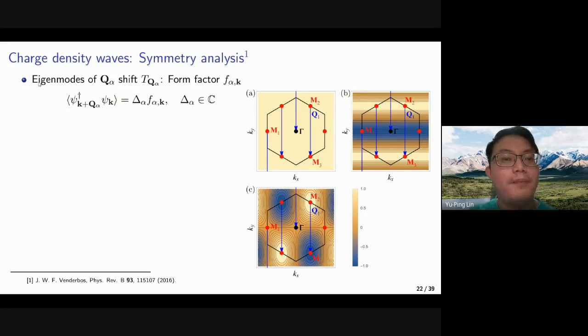So we will want to introduce the charge density waves into our model. The first thing to do is to do a symmetry analysis for the model. The symmetry of the density waves at finite Q can be thought of as the eigenvalue problem of Q shift in the momentum space. So we could define the density wave form factors as the eigenmodes of T_Q, where there is a complex amplitude and the form factor for the psi dagger psi condensate.